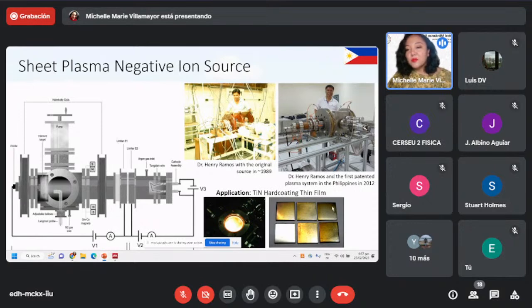These are some sample deposits we were doing when we were optimizing the deposition of TiN. And here is how the plasma looks like. So one of the problems with plasma deposition is the non-uniformity of the sample, and you have to tweak that, and you have to change where the target is going to be placed, where the gas is going to be fed, and how you are going to create the plasma.